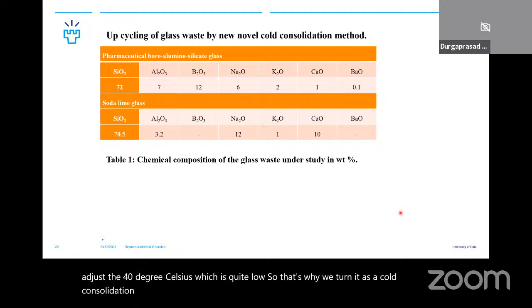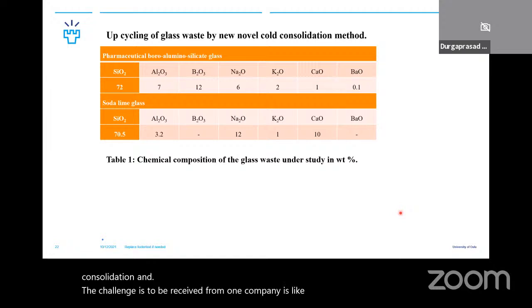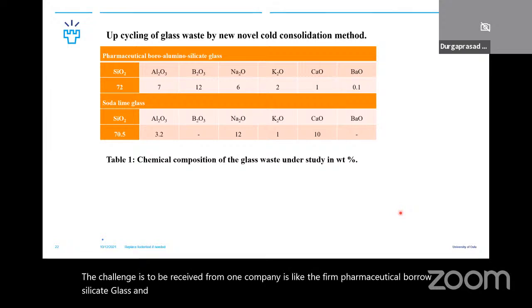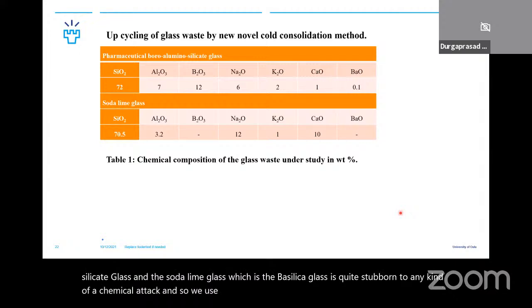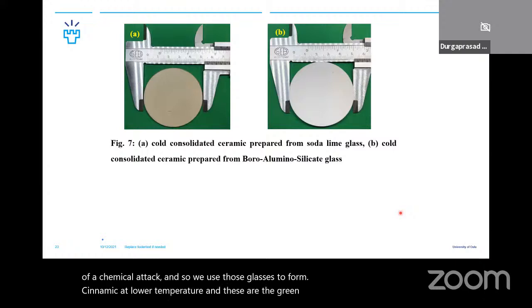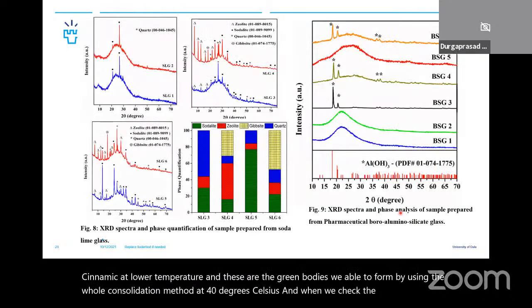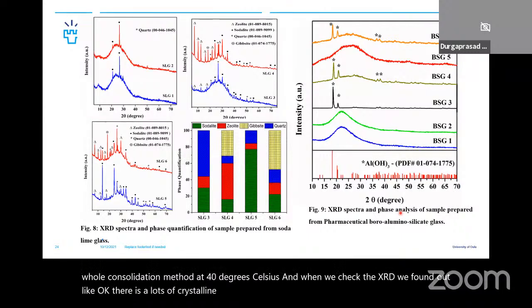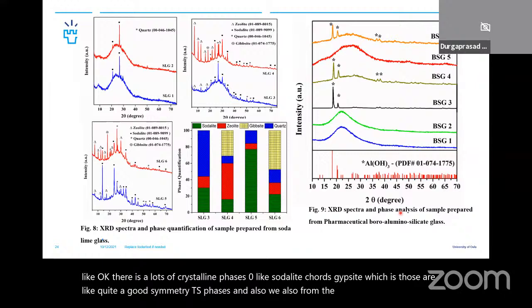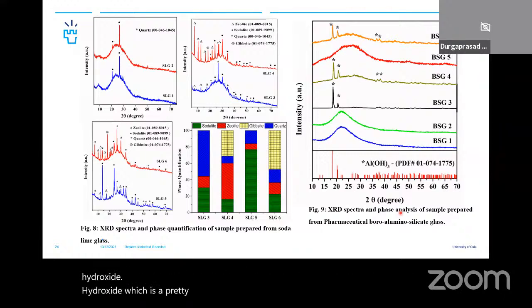The challenge we received from one company was pharmaceutical borosilicate glass and soda lime glass, where the borosilicate glass is quite stubborn to any kind of chemical attack. So we used those glasses to form a ceramic at lower temperature, and these are the green bodies we were able to form using the cold consolidation method at 40 degrees Celsius. When we checked the XRD, we found lots of crystalline phases like zeolite, sodalite, quartz and gibbsite, which are quite good cementitious phases. We also found aluminium hydroxide, which is a stable phase with pretty good compressive strength.